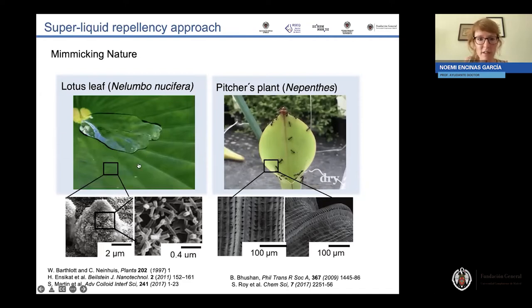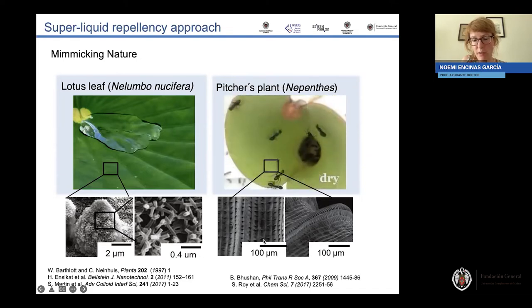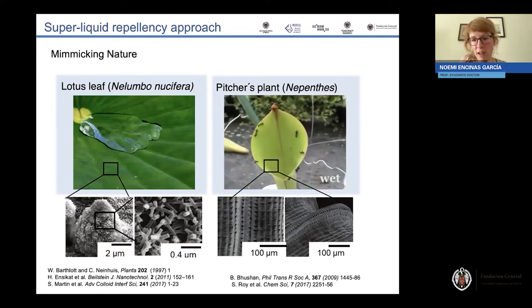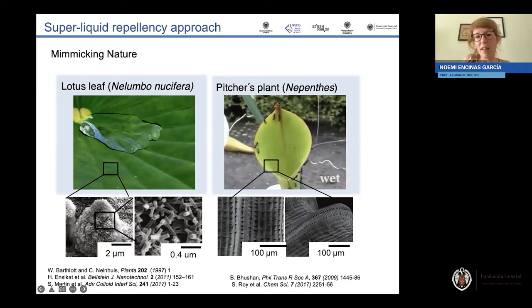Therefore, whenever rain encounters the lotus leaf, basically, this high mobility promotes the capability of the leaf to self-clean itself. Water is going to catch all the dust particles, and as it will roll easily on the surface, whenever it's tilting, it will become clean. Similarly, we can see the behavior of the pitcher's plant. So we also have a certain distribution of channels with a roughness that allows, in this case, ants to nicely walk through the plant whenever it's dry. However, when rain comes and the plant becomes wetted, these channels are going to act as a lubricant. So all the ants are going to go inside the plant and it can basically eat them.